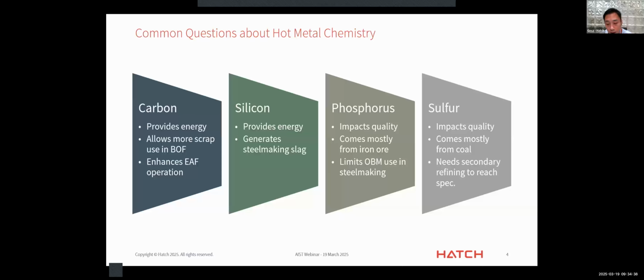Phosphorus and sulfur, on the other hand, are impurities that need to be removed. They come from different sources, but all of it needs to be removed for steel to finally meet the quality specifications. Again, silicon is an interesting one because it provides energy, which is good.